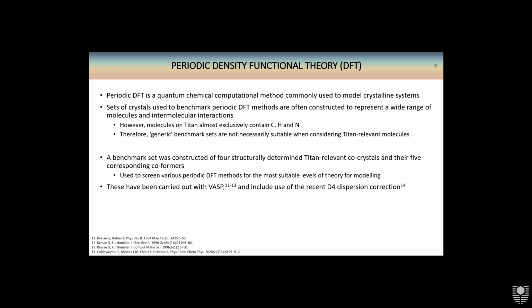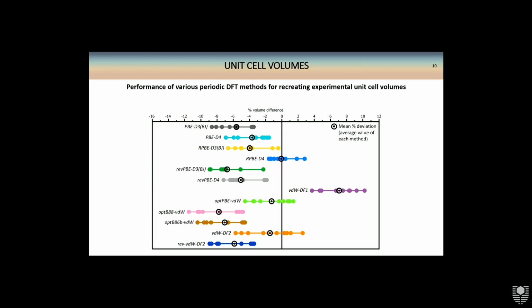So we found it necessary to start by constructing a benchmark set based on just Titan-relevant molecules. We put together four of the structurally determined co-crystals and their five corresponding co-formers, and we've been using these to screen 12 different periodic DFT methods. I've been carrying these out with the VASP program, and notably I've included the use of the recent D4 dispersion correction.